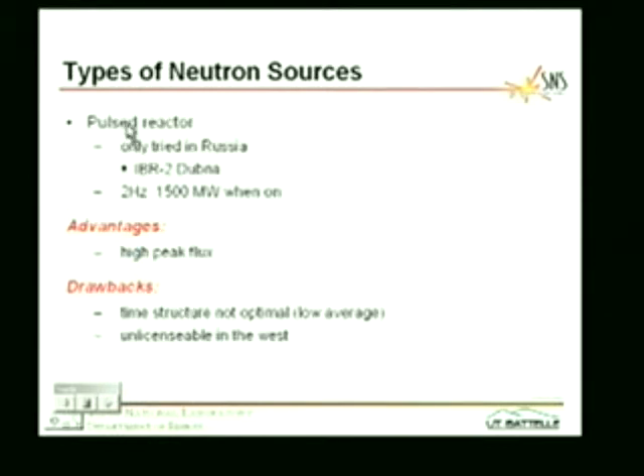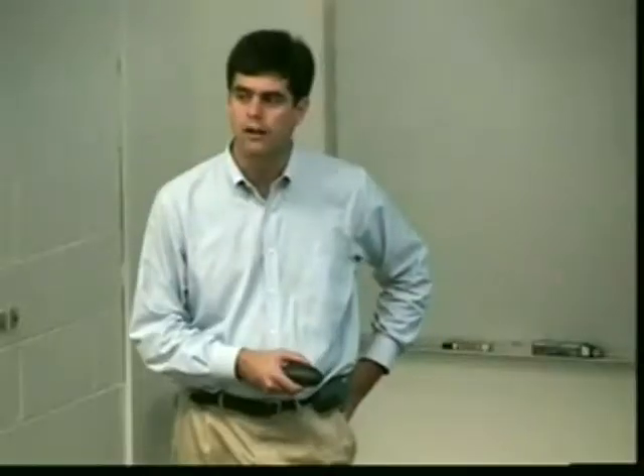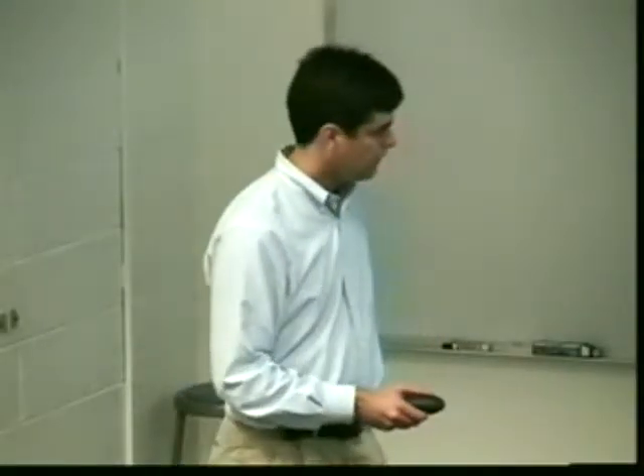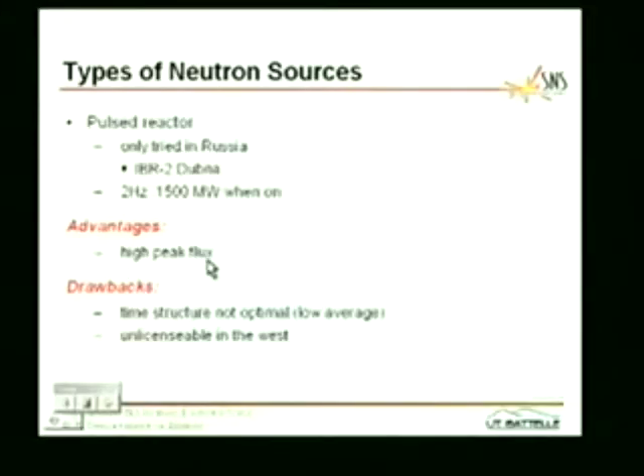There is a variant, which is a pulsed reactor. For neutron scattering, the only one I know of is in Russia, the IBR-2 in Dubna. It ran initially at 2 hertz. They've upgraded it to run at 5 hertz. And when it's on, it's really on. It's a 1,500 megawatt reactor. For comparison, the ILL reactor is a 58 megawatt reactor. And so it has a very high peak flux.